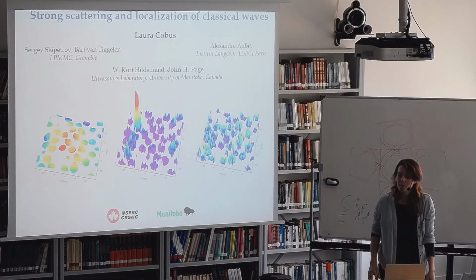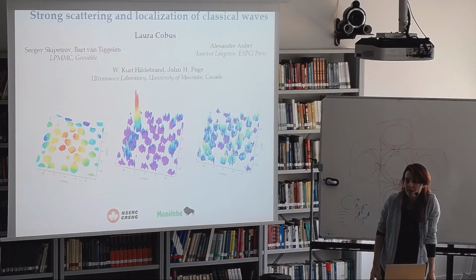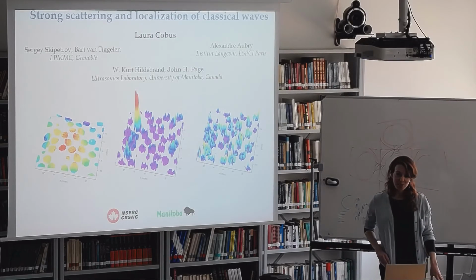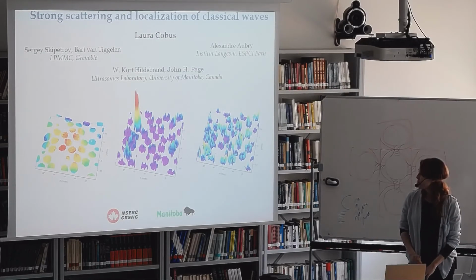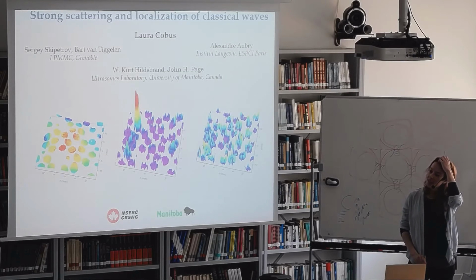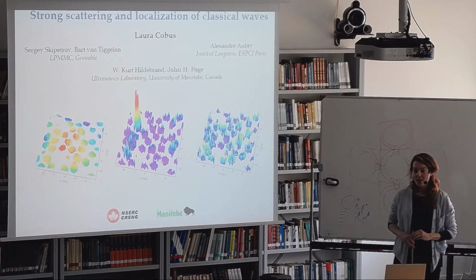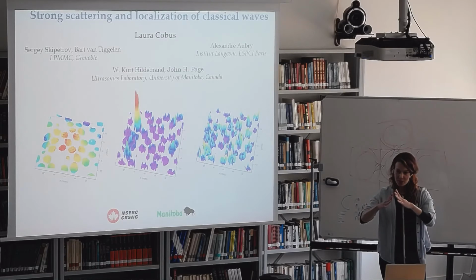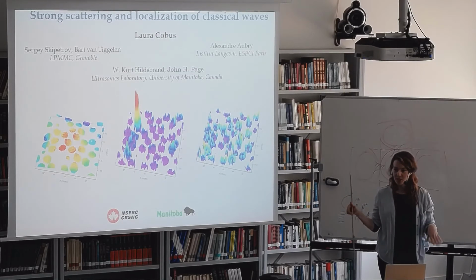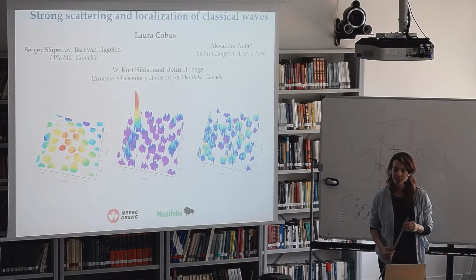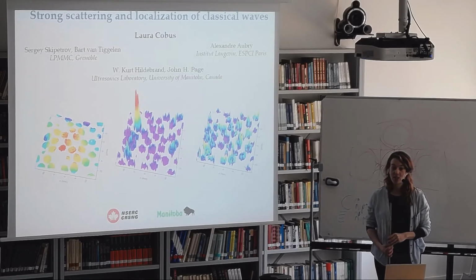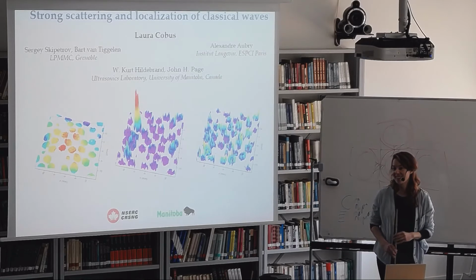So, did you try to fit your data for the Anderson localization to find a critical exponent? And does that work with the theory? We did try, but it did not work yet. It's very hard because, well, one of the reasons that it's very hard is because at this critical regime, you just have a crazy amount of fluctuations. And so you need a lot of configurational average, like a lot. And so we didn't have enough.